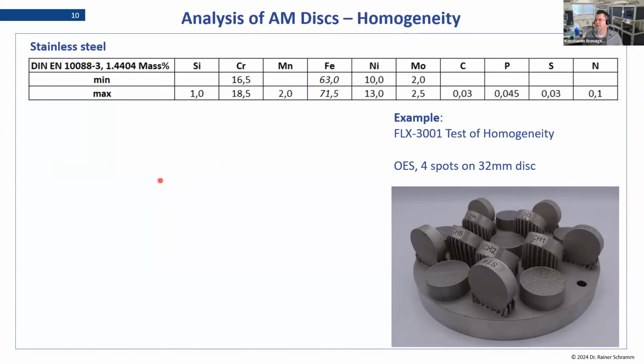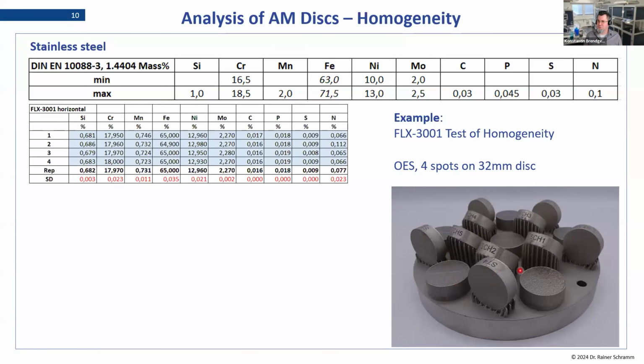The next step that was made is then to test the homogeneity of the actual product, the actual printed part that we are doing. How homogeneous is this? And to do that, we actually collected data from a different laboratory, and the idea here was that we make this kind of modern art, let's call it, and then we measure it with an optical emission system at various points to see how homogeneous is the actual piece that we are making here. And you can see here as well, if we're making horizontal measurements on this flat surface, we get a very nice homogeneity of the sample.